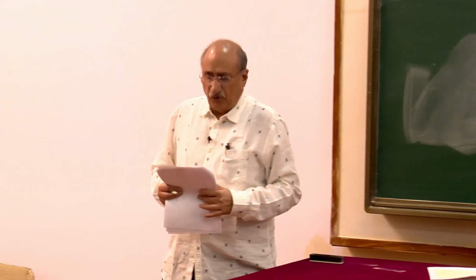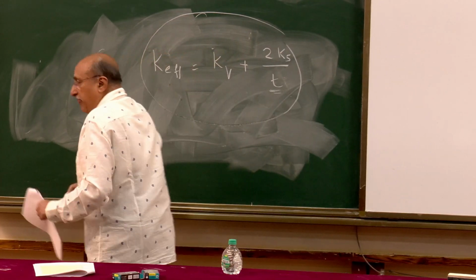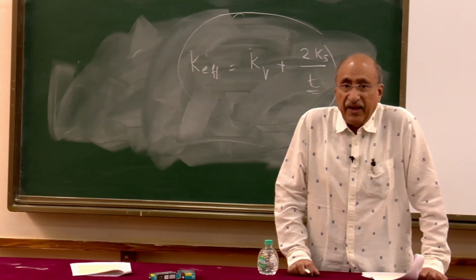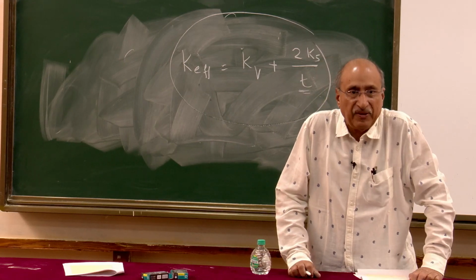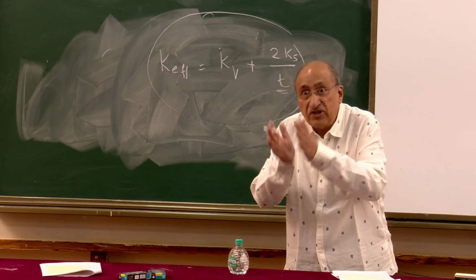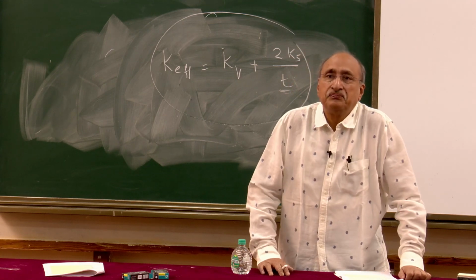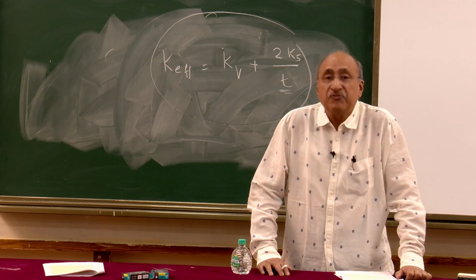Generally this is for a uniaxial system, because uniaxial systems are much more in use when we are talking about anisotropy. People are generally using uniaxial systems anyway because they have large anisotropy. So, if you go to a very small t, you will be able to make the overall film much more anisotropic. You can increase the anisotropy, and therefore you can change your loop. I have told you that anisotropy is one thing with which you can change the loop. So a large number of people developed, using this idea, an anisotropic material where originally the material did not have that type of anisotropy. But just by making a multilayer, we used surface anisotropy to enhance the anisotropy of our system. This is another use for which people were using it.